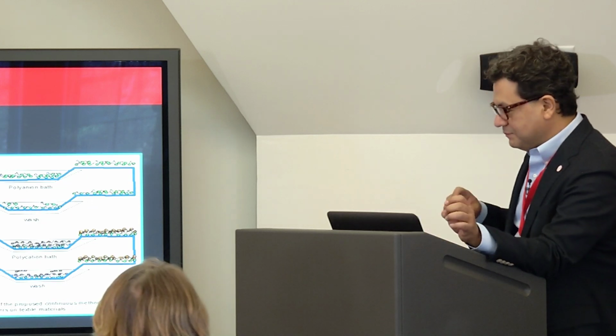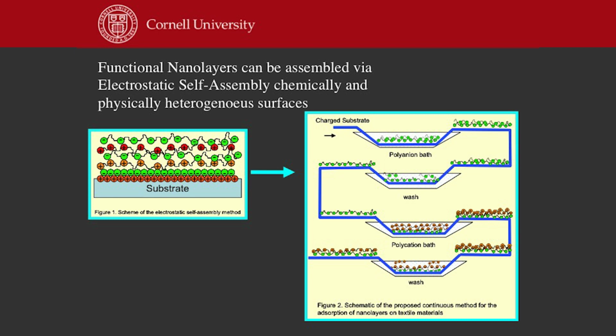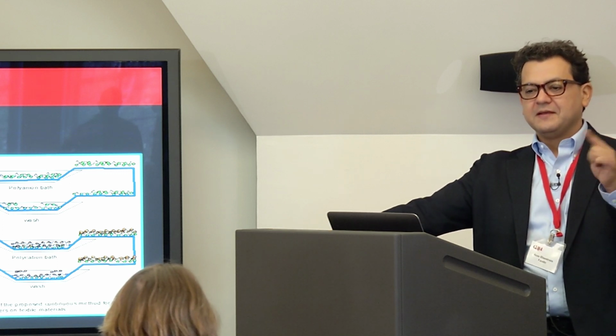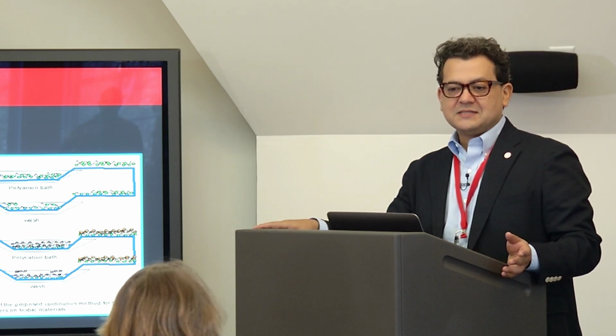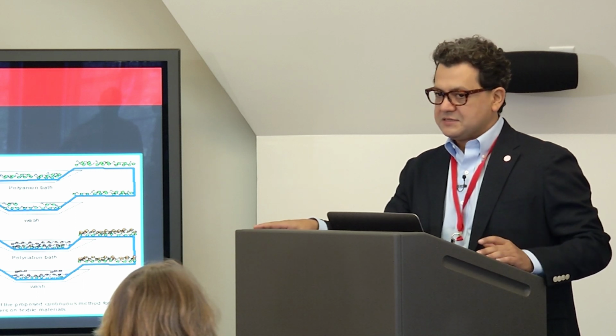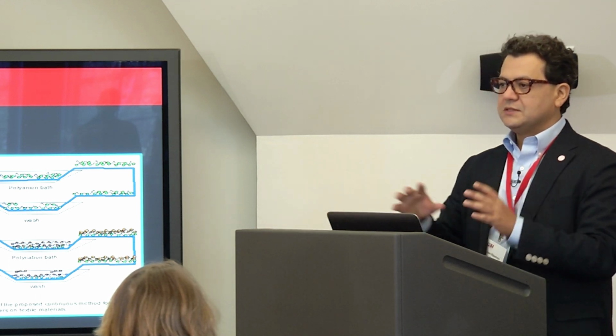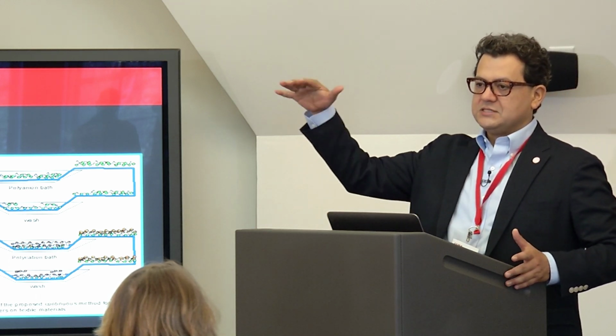So to do that, I use a process called self-assembly, in which I deposit molecules one on top of the other like a sandwich. So I put one that is a positive polyelectrolyte, one that is a negative polyelectrolyte, and I put them one on top of the other, and each one of them will be able to control a specific chemical. Now, this was a very challenging proposition because this method only worked for surfaces that were flat and homogeneous. The main issue is I wanted to use cotton, which is not homogeneous and is non-flat. In fact, the cotton from Alabama is different than Texas, and is different in July than in August because of fertilizers, because of weather. So you have to develop tools that will be robust enough to overcome all these issues.